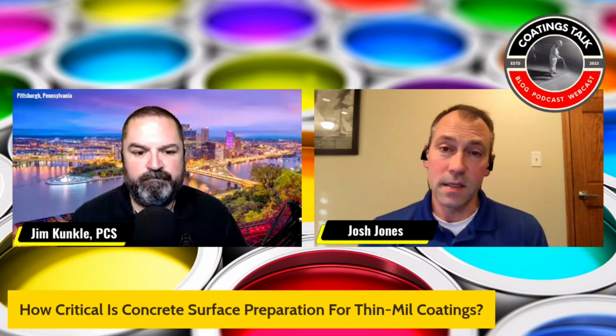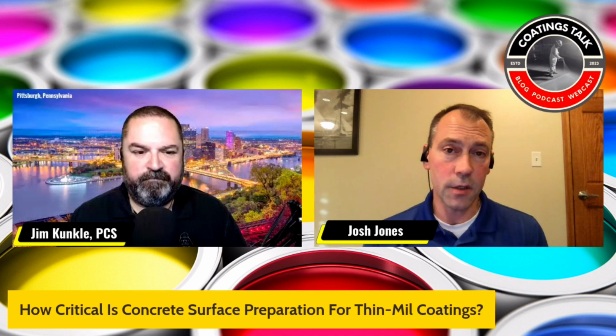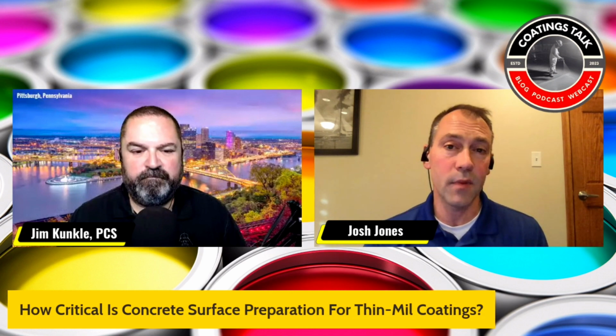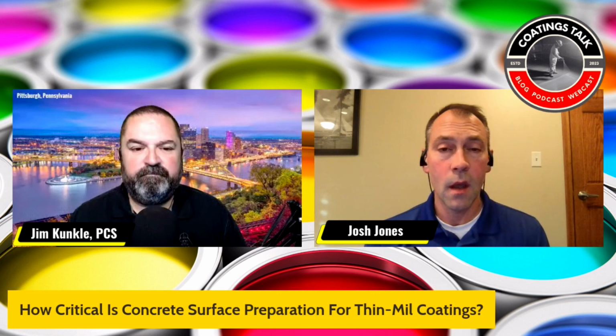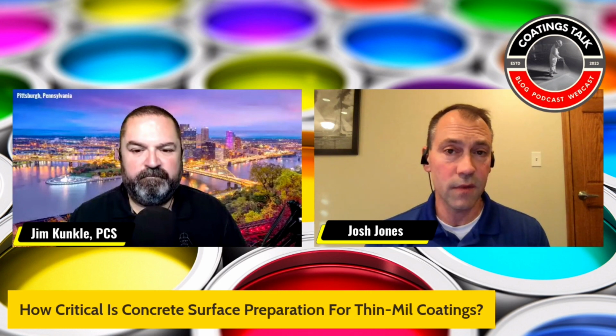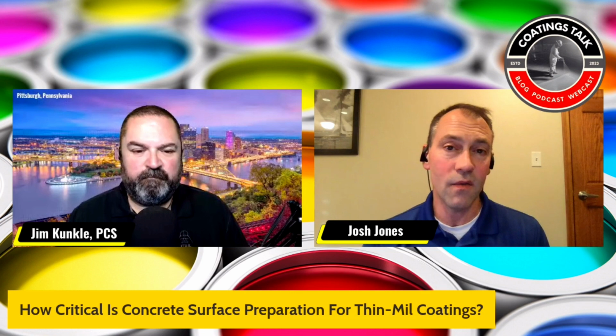Considering that concrete, as I said, and this is a good thing for adhesion, concrete is absorbent. So that means if I can make the floor clean of any surface contamination and encourage it to be absorbent to the maximum capability that it has, when I put a liquid coating on top of the floor, because all these are fluid applied materials, they're formulated that within a certain amount of time to absorb in the surface matrix of the concrete to whatever depth it may be. It's not very much, a few mils, maybe even up to a millimeter, usually a few mils, so that's quite a bit. The idea is that there's nothing to inhibit that absorption.